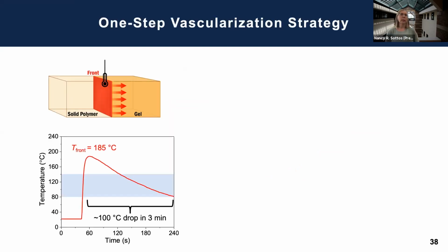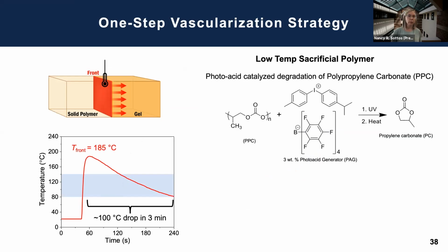So this is a snapshot from a thermocouple of what the temperature profile looks like as that wave propagates through a polymer. In this case, the Tmax is at 185, and we have about a 100 C drop in 3 minutes. So really, these are the conditions we have to work with to depolymerize a sacrificial template in the way that we've done before, if we're going to use the frontal wave.